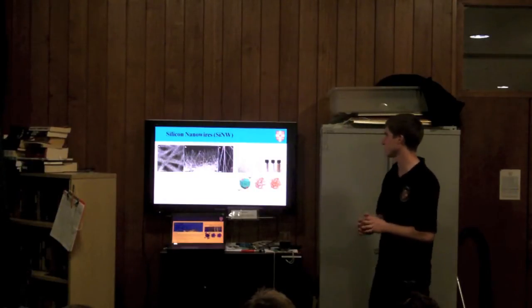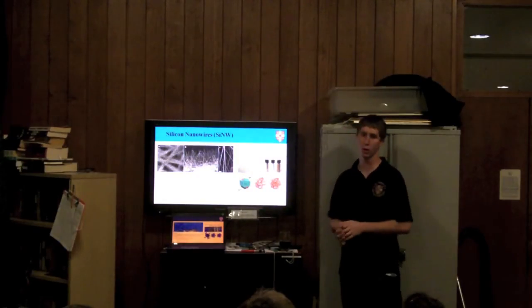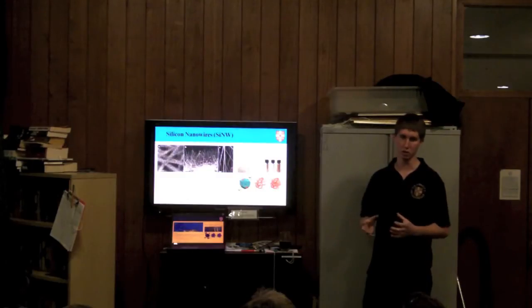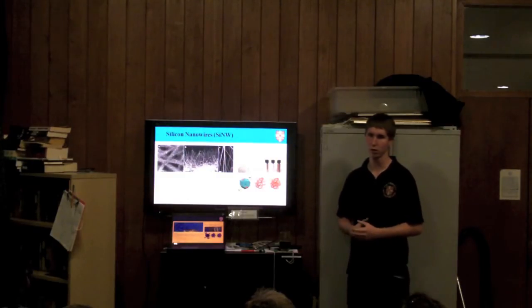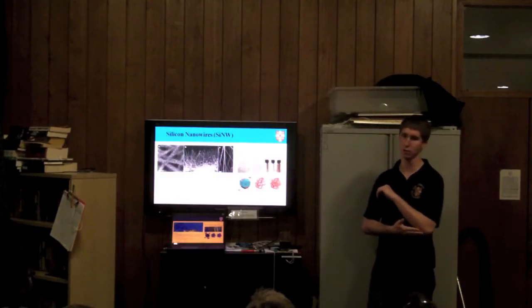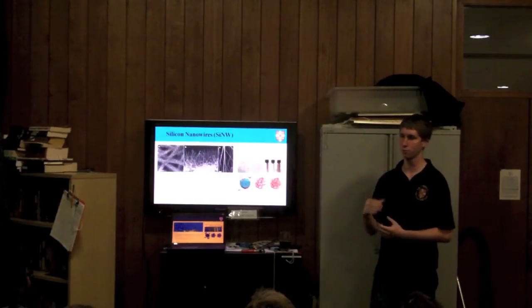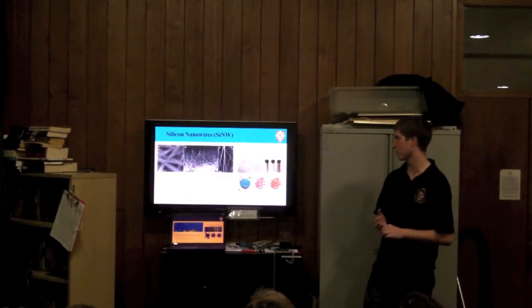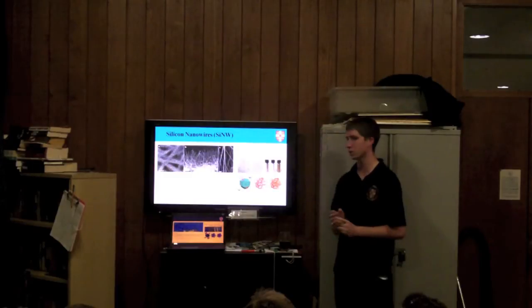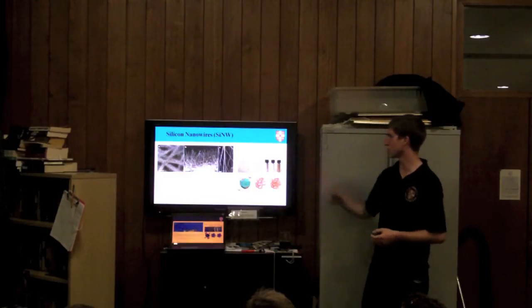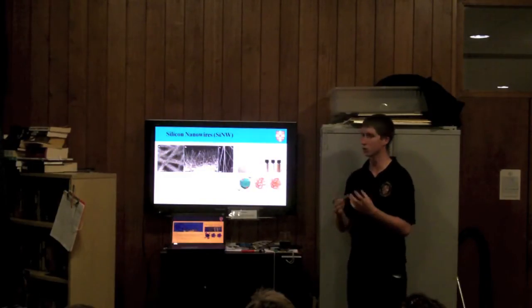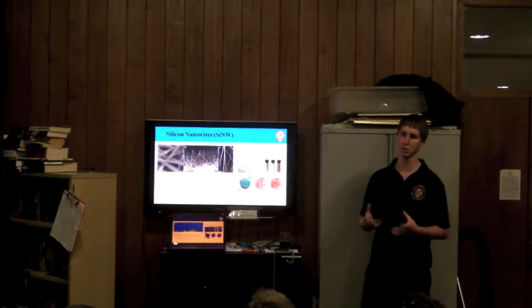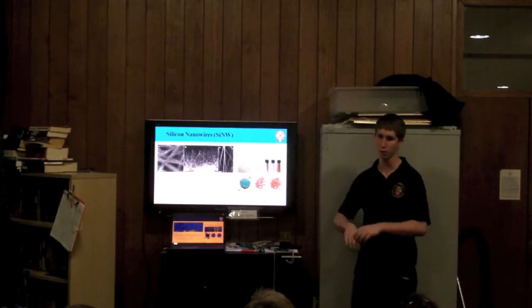And so that's why rather than even saying silicon, I've already just called this silicon nanowires, because you can't just stick in a chunk of silicon. It doesn't work. So you have to come up with some geometry that's more sophisticated. And right now the thing that's working best are these nanowires, because you imagine if you grow this mesh of nanowires as these images show, those things might be able to expand 400% and still be stable, right? If you just put in a block, the whole thing's going to break up.